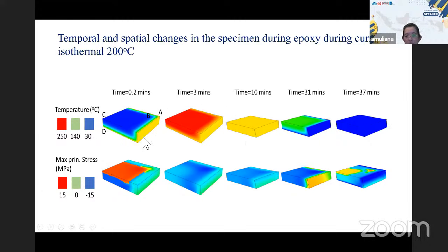So we see expansion as the polymer becomes larger due to the expansion effect. As it cures, it shrinks. Now at the final state, you see we have all this uniform room temperature after cool down, while we still see here what we call residual stress, and also there is warping in this polymer due to the non-uniform shrinkage and non-uniform expansion. This is actually unwanted, I might say, right? So as much as possible, you don't want to have warping in the polymer sample.